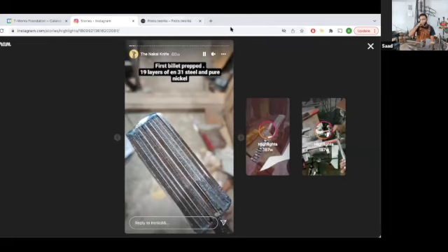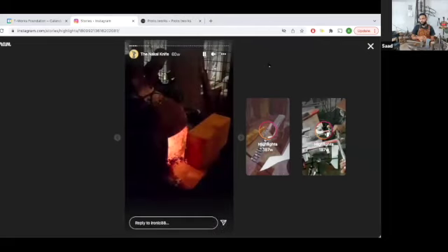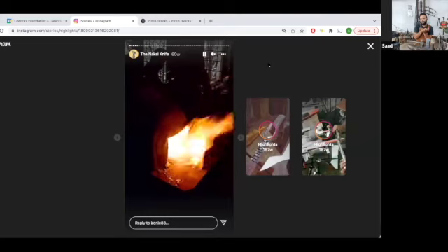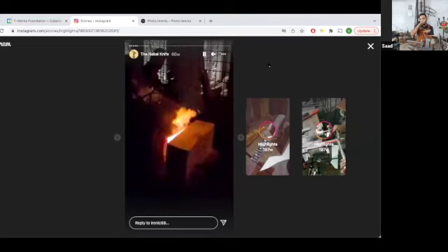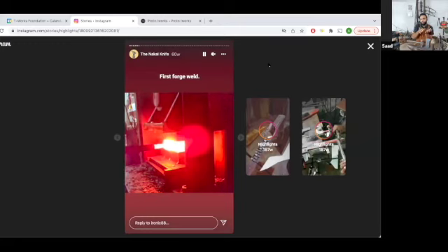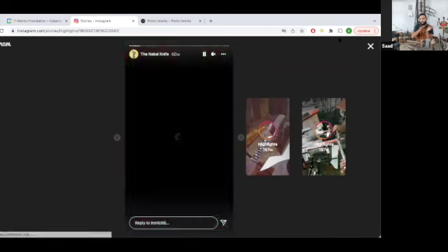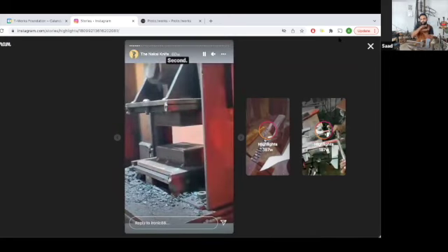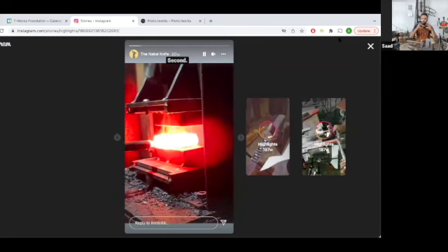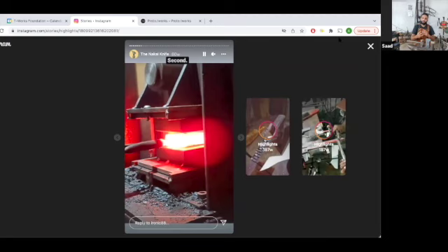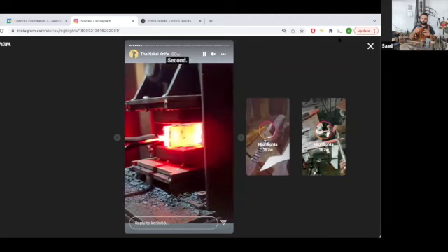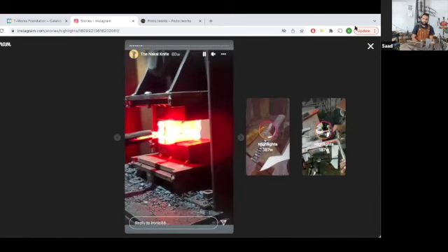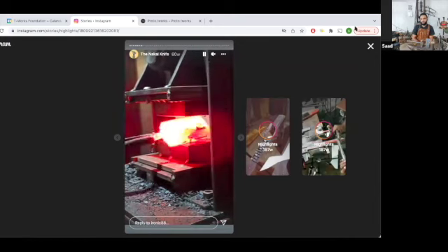Here's the initial billet, and you have to bring it up to a certain forge welding temperature. Too cold and the pieces don't stick to each other. Too hot, and when you're trying to smash the pieces together, they fall apart. So you have to balance temperature and force. If you hammer too hard when the pieces are at a near molten state, they split apart. So you've got to nudge the metal and convince the layers to weld to each other, and then it becomes one solid block. Then you manipulate those blocks into different patterns, and you get a Damascus pattern out of it. So in essence, that is what Damascus steel is.